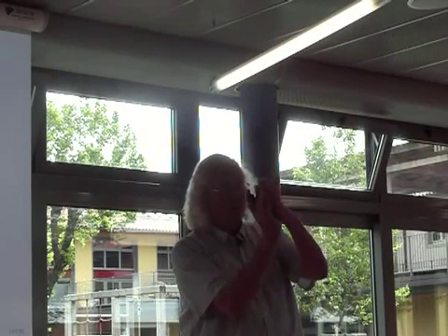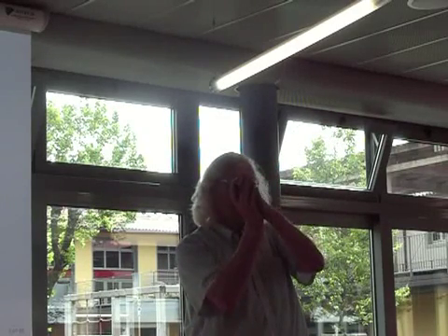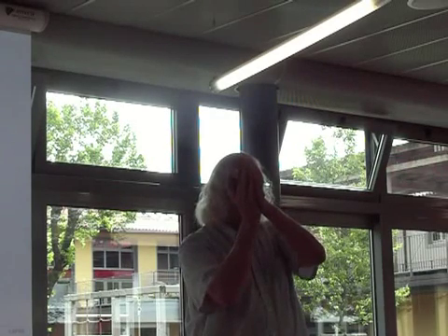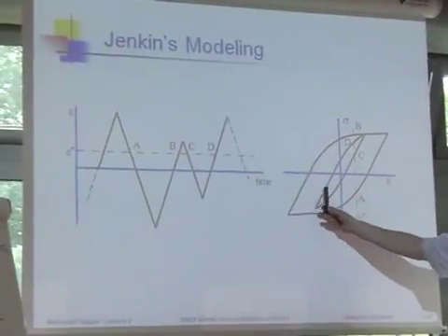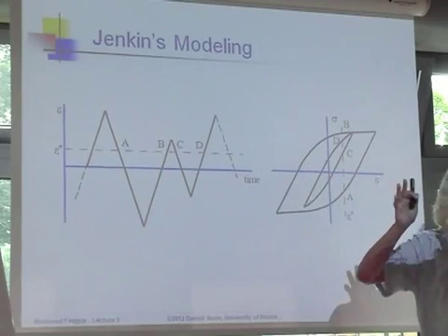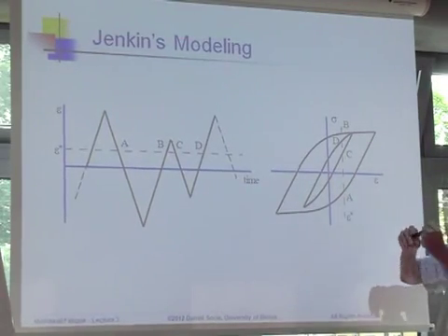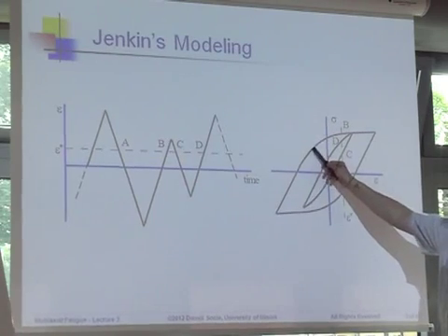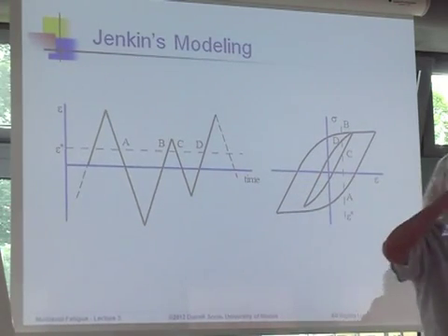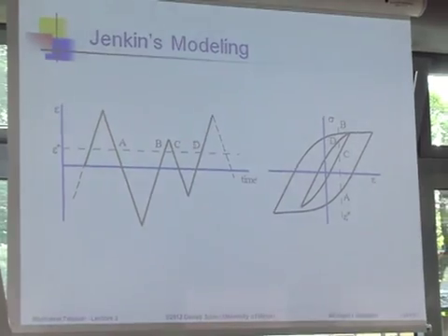And you know, we've really been using that for the last day or so, right? Because I have been talking about what we see about all these microcracks, and we think about stresses opening the microcrack. It's not the strains, but it's the stresses that open that microcrack. Right? I could have compressive strains and tension stresses. No problem. Right? Just think of a point back here. I have strains which are in compression, but I have tension there. And so if I had a little microcrack that was there trying to grow, it would grow because I have tension across that crack. Okay, that was what Jenkins did back in the 1920s.